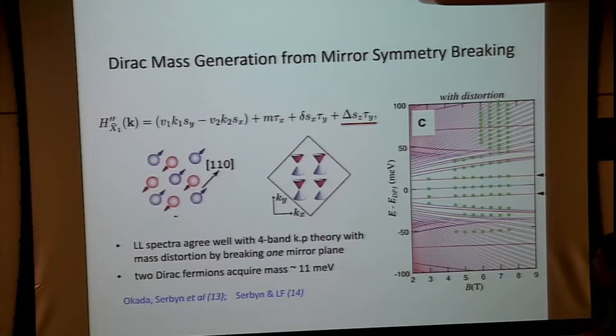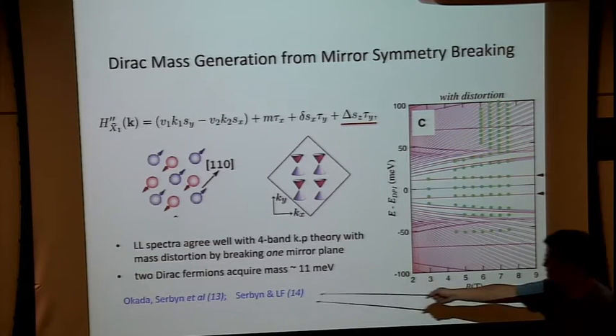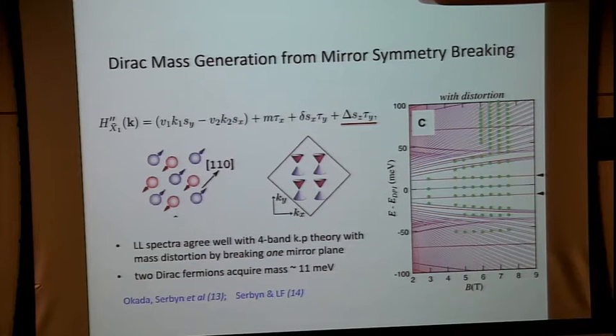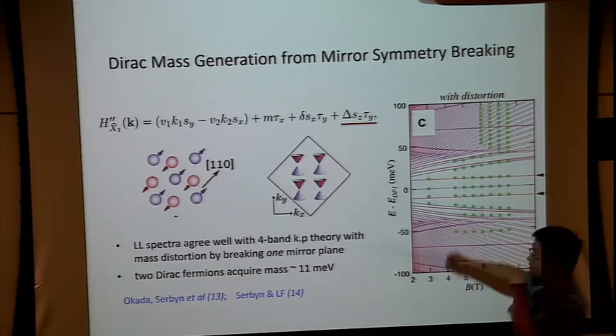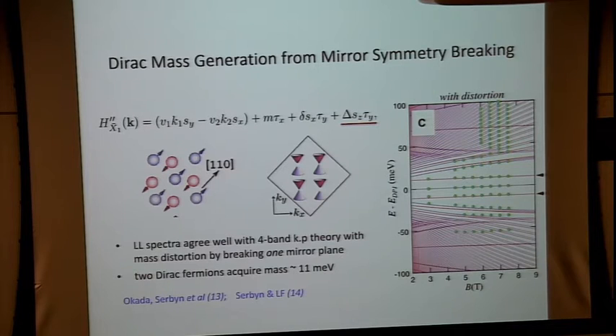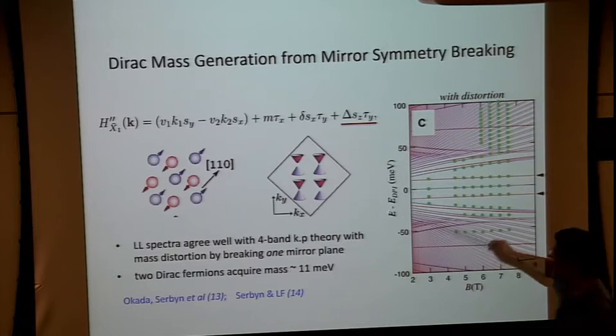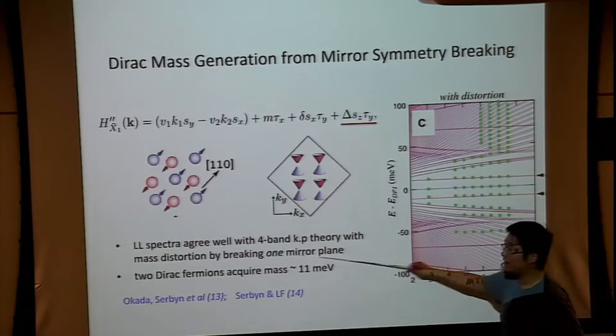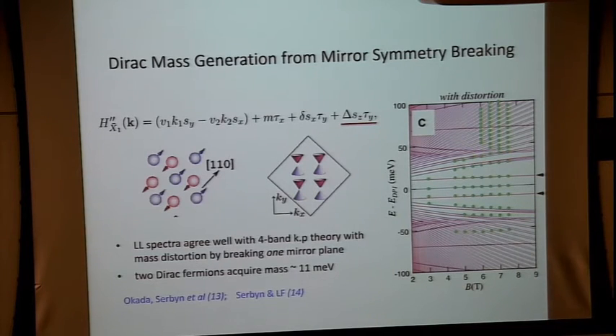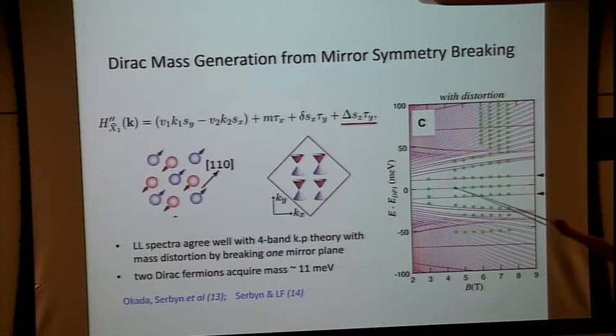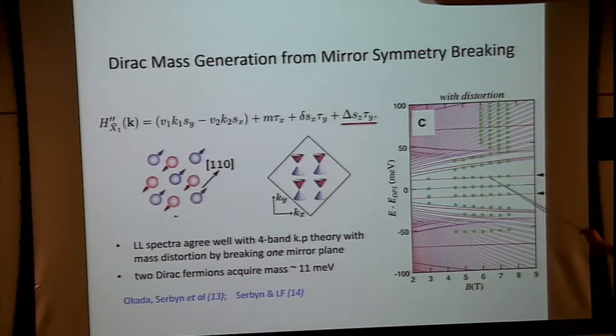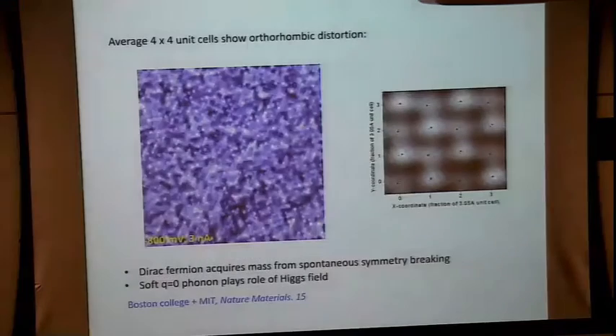So with a former student, Maxim, we are able to fit the Landau levels over a wide energy range by just using 2 parameters. And actually, from this experiment, the Dirac mass we inferred is 11 millielectron volts. Basically, it's the energy spacing between the non-dispersive Landau levels.